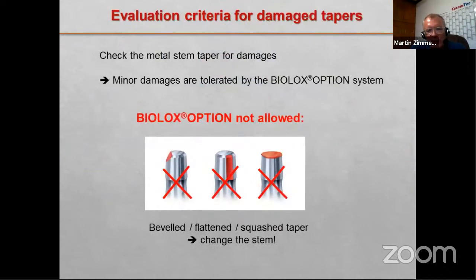But there is some limitation. The sleeve system has limitations, as you can see in these three schematic pictures of the deformation you can have on the stem taper. If you put the sleeve on the taper and there's waggling, and you feel the impression is not stable, then it's recommended not to use this system and most probably to change the stem. But if it's too difficult to change the stem, then use a metal ball head.